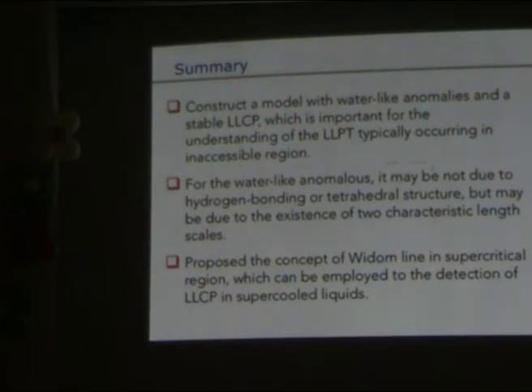First of all, we basically want to understand the liquid-liquid transition, based on the supercritical phenomenon in the liquid phase. We constructed a very simple model. This model has all the water-like anomalies. Not only that, it also shows the hydrogen bond behaviors being taken out, so this is quite a general model. This model has a very stable liquid-liquid transition, which is really important for the study of this critical phenomenon. Therefore, we can explore everywhere in the phase diagram and compare with experiment.